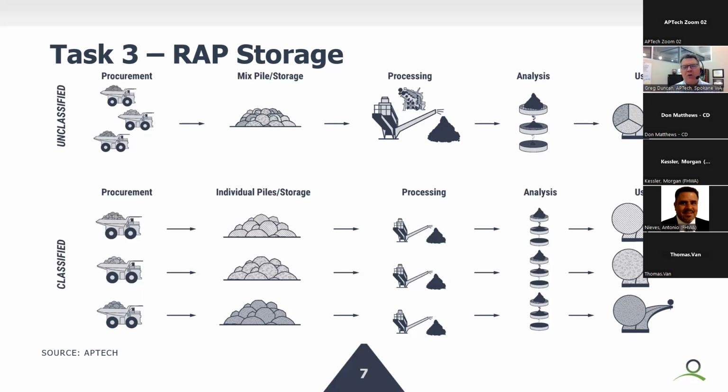So because we're using an asphalt coated rock, typically we're worried about what's the temperature, what's the humidity, what's the likelihood that those materials adhere to each other. My recollection from our interview is that you want to be using those materials within just a few days of being processed, so that risk doesn't happen. From an equipment standpoint, we may need to have reprocessing equipment available at the satellite storage locations if materials are processed and then carried to a central site where we might feed a chip spreader from, or a chip seal operation in that regard. We may need to have additional processing there. The same is true for the fine aggregate materials that would be used in slurry systems.